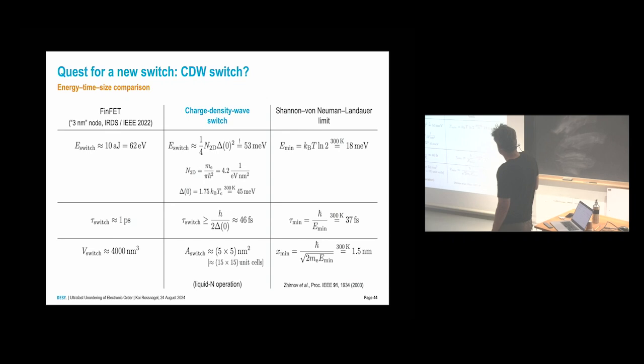So, the Shannon von Neumann-Landauer limit. To switch a bit at room temperature, you need 18 meV. This would correspond to 37 femtoseconds and a minimum size of 1.5 nanometers. So at least conceptually, we are not so far away from this. But of course, this will never happen. You will never have a charge density switch. It was just a conceptual idea.